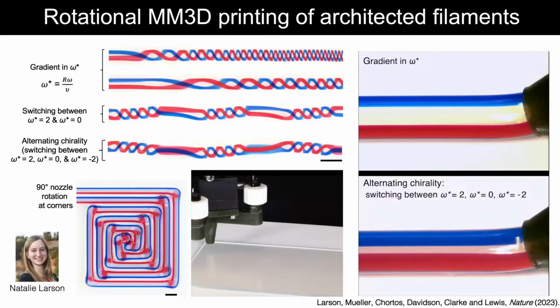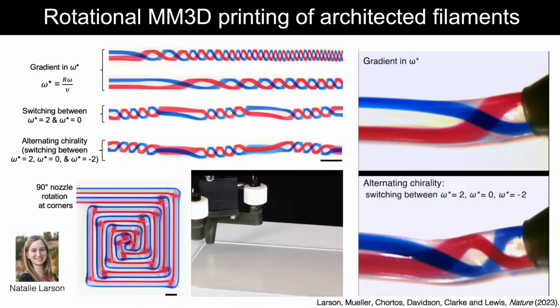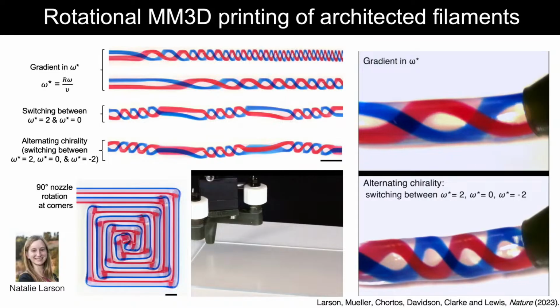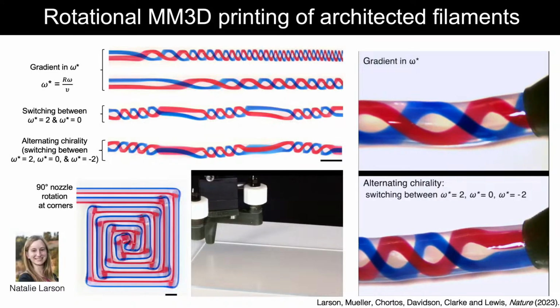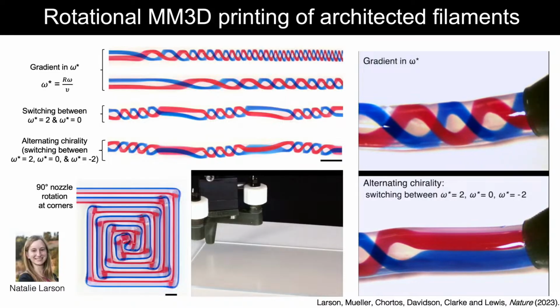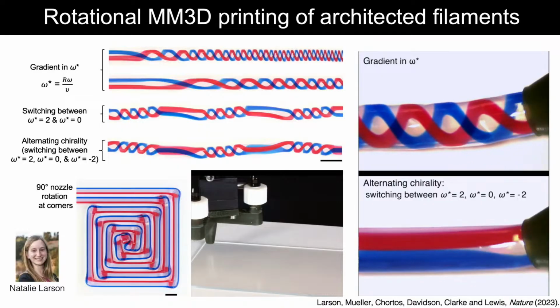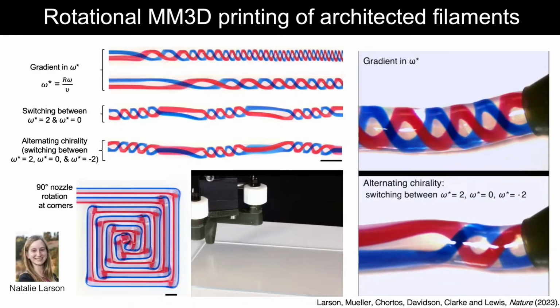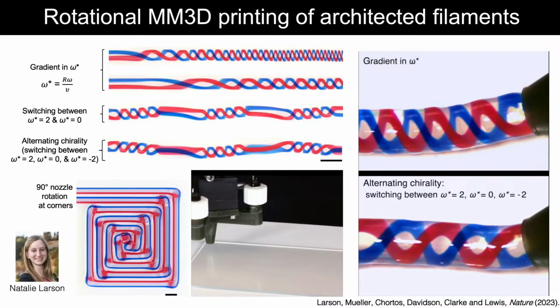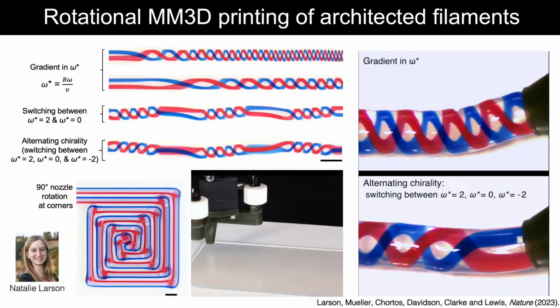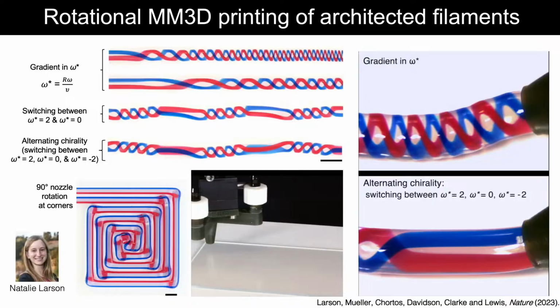And so let me play these movies. Good, they're working. And so then just simply by changing the nozzle geometry and or the rotation rate, we can start to create gradients by changing the relative rotational rate, or by alternating the sign of the rotation to create alternating regions of opposing chirality.